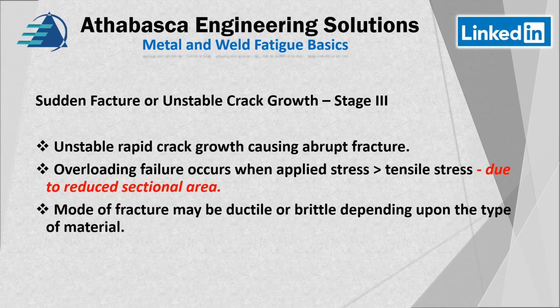So it's an overload fracture, and it may be ductile or brittle. It depends on the type of material and how it fails, because sometimes the part at the end can neck a little bit and then fail if it's high ductility, or if it's like cast iron, it'll just suddenly snap and break. And so it exhibits those properties. And of course, that's all temperature dependent, because if you have a very, very low temperature material and it's not rated for those temperatures, then even a ductile material can act like a brittle material, right? If you want to know more about it, it's called MDMT, and it's found in our earlier videos. We made a whole bunch of videos on that, so we can understand how those engineering issues are handled.